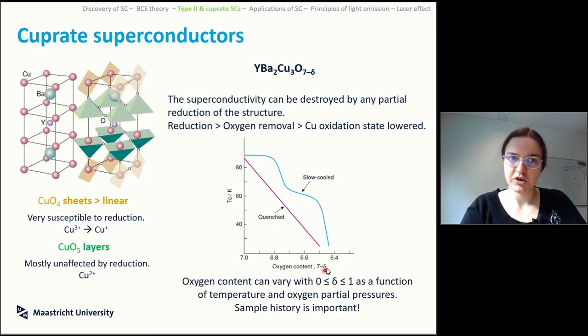So the oxygen content, depending on how you try to control it upon synthesis, could lead you to a plateau of very specific temperature of transition of superconductivity, or you can get a smooth line. If you don't make it properly and this thing is maybe completely oxidized, your material is simply not superconductive, which can happen, but is not what you want to happen.